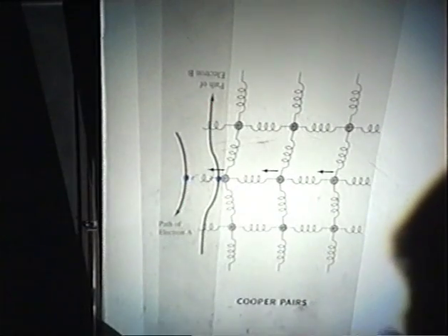All the Cooper pairs pile down into the lowest energy state available, and in doing so, all the Cooper pairs become correlated, and you sort of have something like a giant electron molecule in the lattice, which just propagates through as if the lattice wasn't there, because it's not energetically favourable for any scattering events to occur.